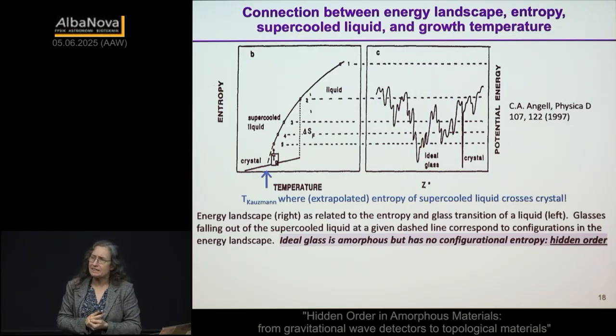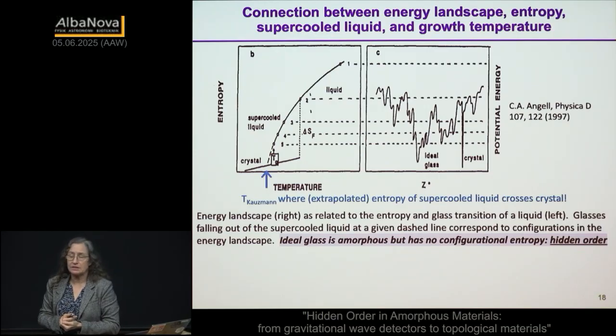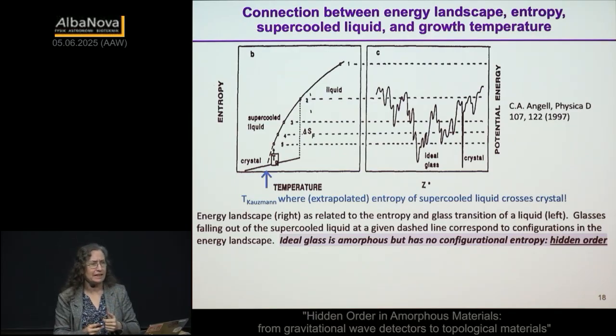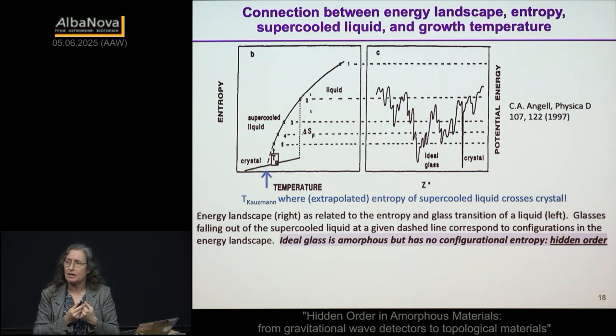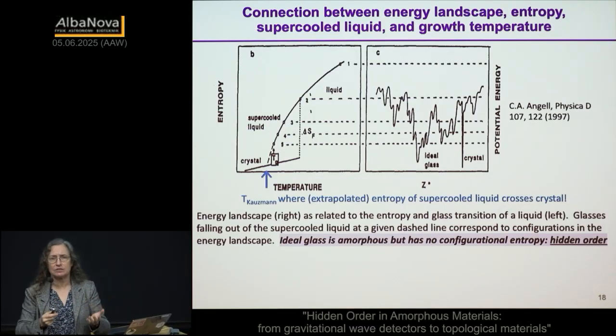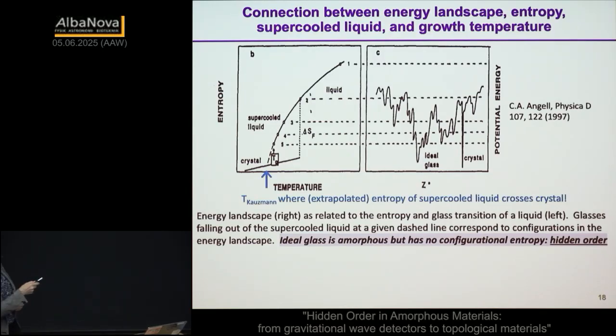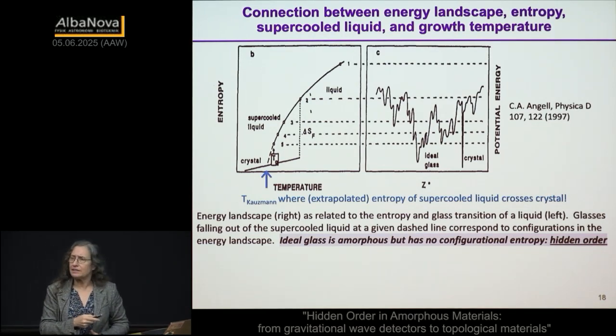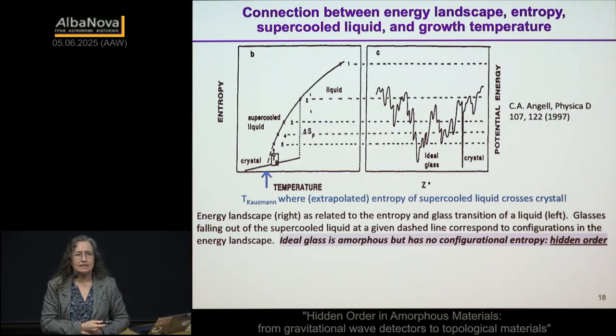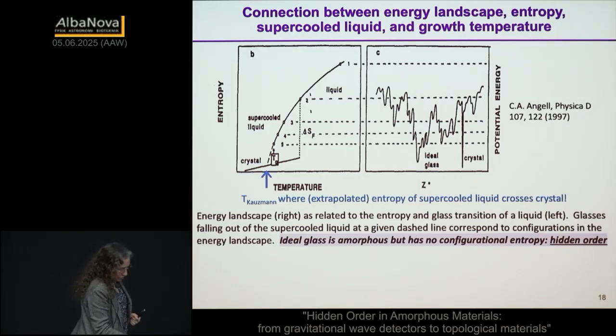So what is it that makes that state unique? It has a ton of short-range order, probably has some medium-range order, doesn't have long-range order. But what really underpins both energy and entropy in the end, if you think of them as having to do with atomic bonds? It's all local. All energy is dominated by the nearest neighbors. So I would claim it's not even that surprising. This is, in fact, a calculation of a Lennard-Jones potential. We claim it's not even that surprising that there should be a unique lowest energy state, and so we call that the ideal glass. That ideal glass has no entropy, has a low enthalpy.